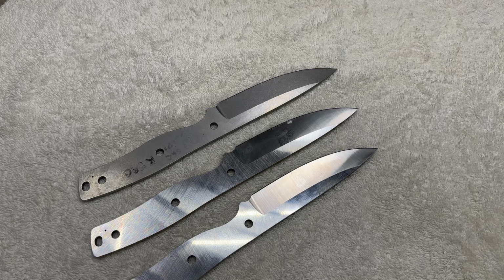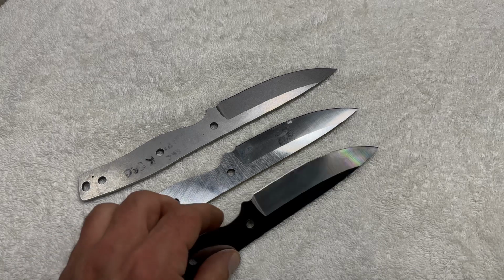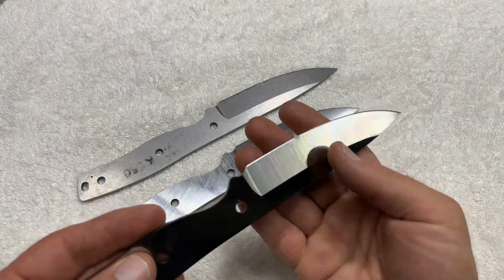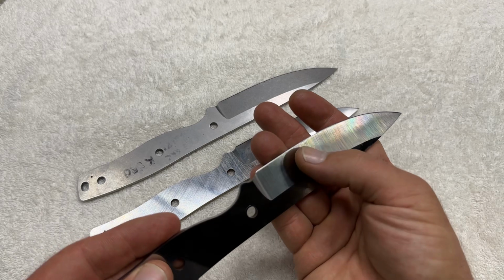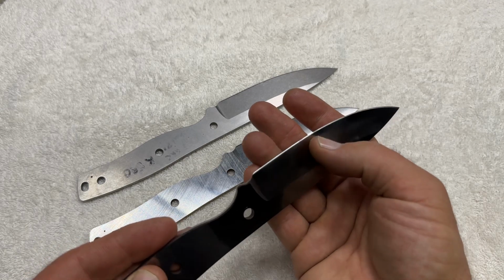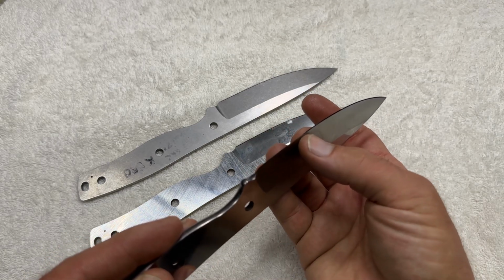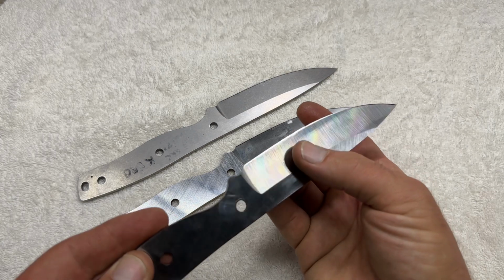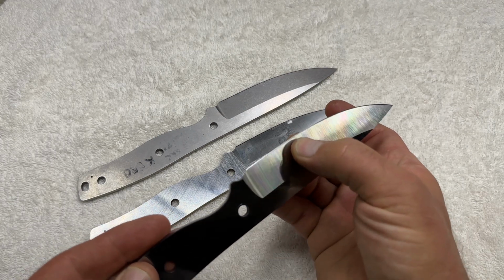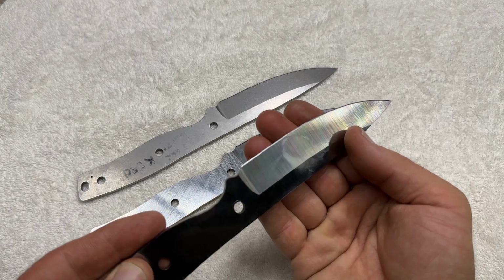So, saving the best for last, the K890 from Böhler. They all did pretty equally well. I think on this low temper sample, all of them just had a little bit of deviation in the panel, but very little apex deviation. That is just because of the very, very thin geometry behind the edge, but no failure.